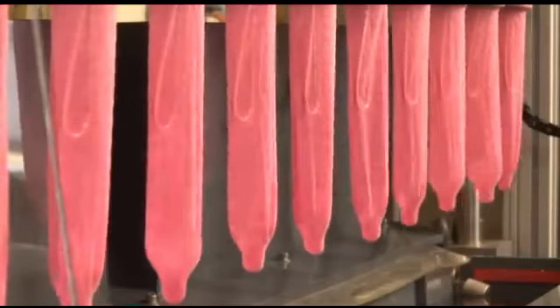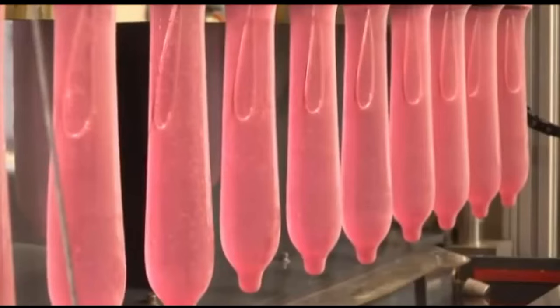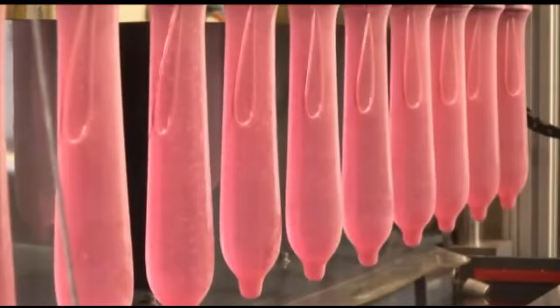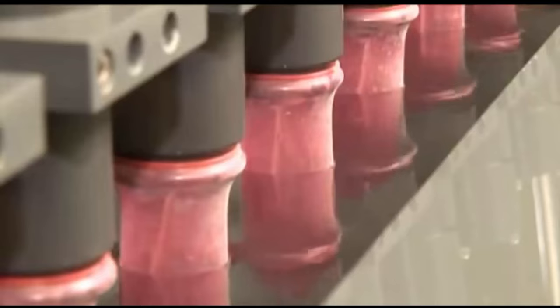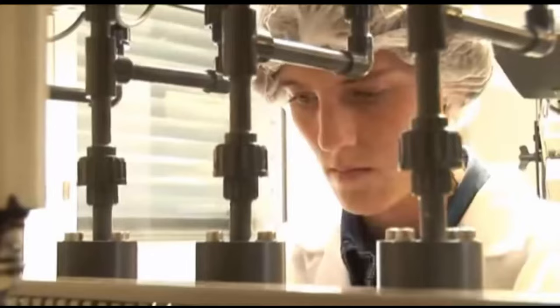Finally, another pinhole test completes this series of tests. This time, the condoms are placed over an electric conductor and filled with water. Then they are immersed into a water-based solution to check whether any condom tested has a pinhole. If the electric circuit between the conductors in the condoms and the voltage source in the basin closes, one of the condoms has a pinhole. Such microholes are not visible to the naked eye.